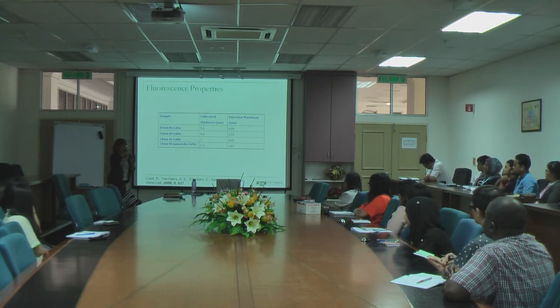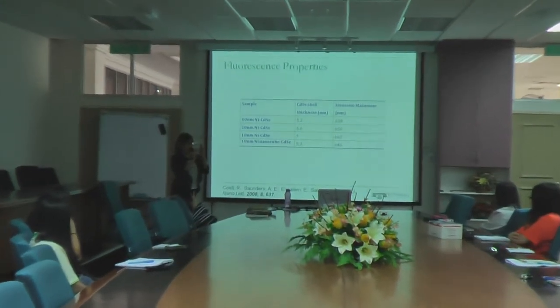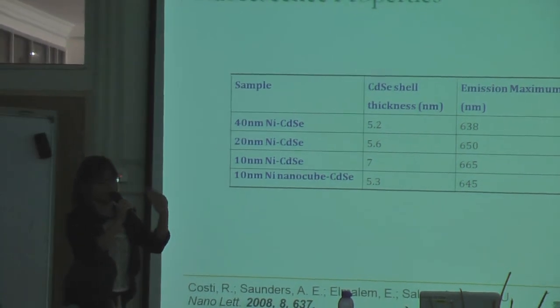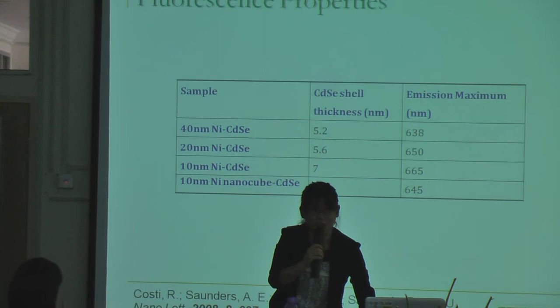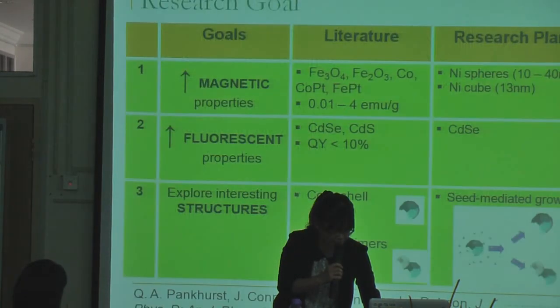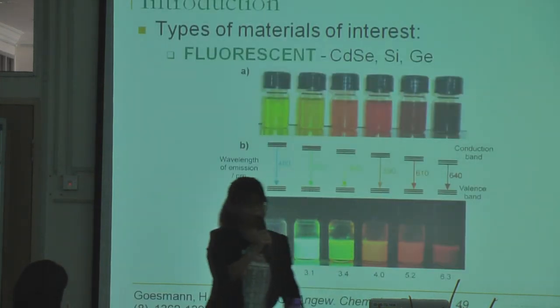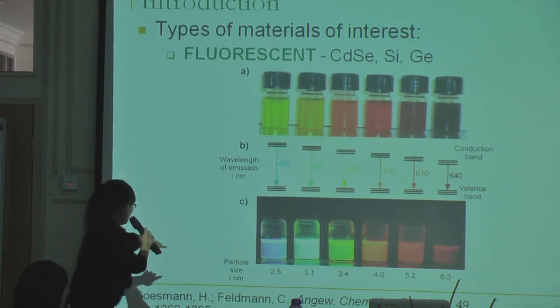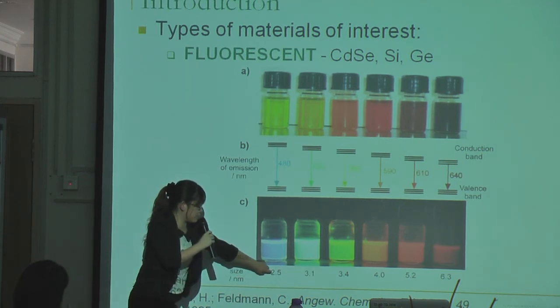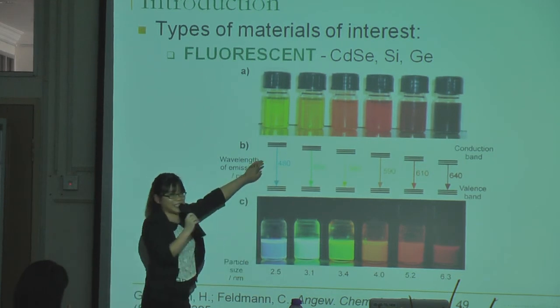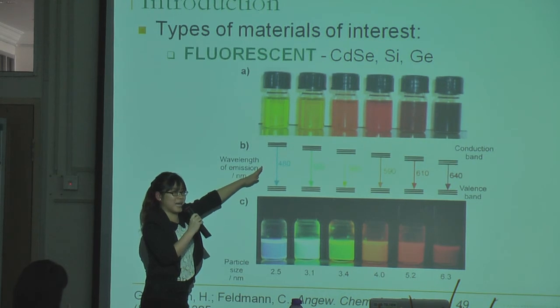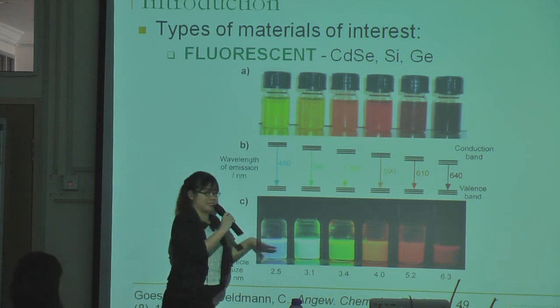I'm not 100% an expert in this, but based on my understanding from a chemist's point of view and its relationship to nanoparticle properties, as the nanoparticle size increases, the material will fluoresce at a higher wavelength. This has been shown by many works on quantum dots research. One example is cadmium selenide. When the particle size is changed from between 2.5 to 6.3, it has a direct relationship to the band gap, and this is quite unique to nanoparticles. And then we can see that the fluorescence is also in different colors.